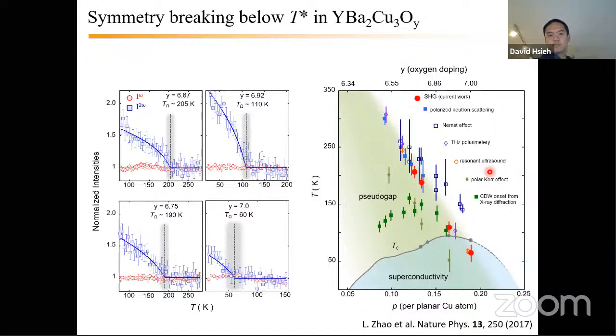And so at least at the time that we published this work, well, in the neutrons, they had already pointed towards the possibility of inversion breaking. And so our data, the fact that you don't see anything in the linear channel and something pops up quite strikingly in the nonlinear channel, really reminded us of that and pointed towards some underlying order that breaks inversion symmetry, okay? And I just want to add that there are no anomalies that we could detect at these other critical temperatures that were measured in other parts of the phase diagram. So it's something happening at T star that lifts the second harmonic intensity.